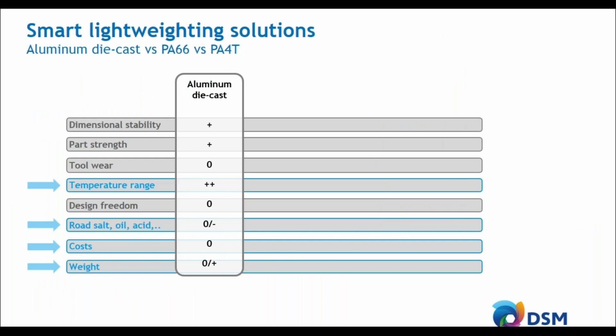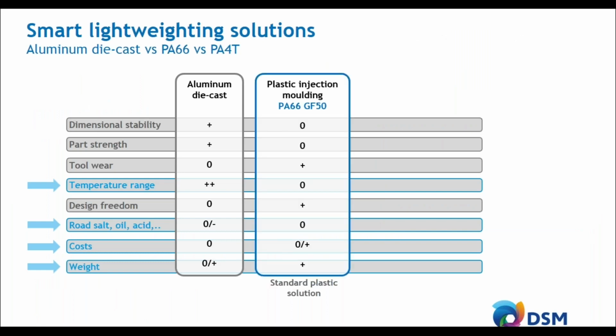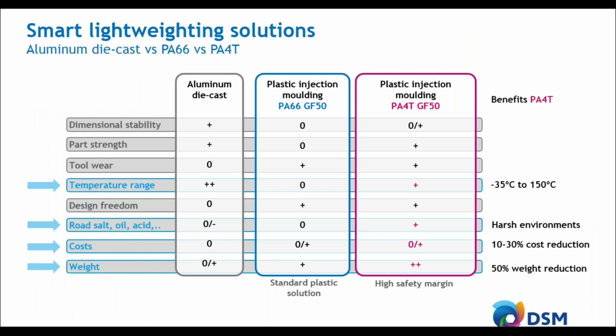So let's make a short recap of aluminum die-cast, polyamide 6,6, and PPAs like polyamide 4T. Choosing the right polymer is very important for your part. We already addressed the temperature range. With aluminum, you can make a design up to 200 degrees C, where you still keep stiffness and strength. With polyamide 6,6, you see a significant drop in strength and stiffness at 70 degrees. With PPA, you can make a design up to around 150 degrees C, meaning that PA4T is really the next best alternative to aluminum die casting.